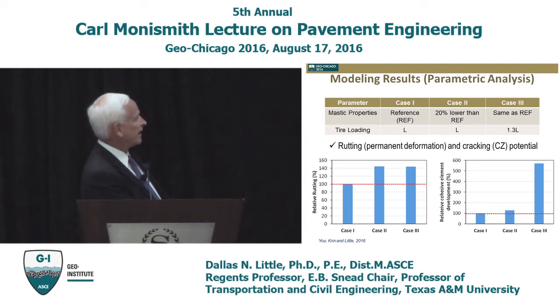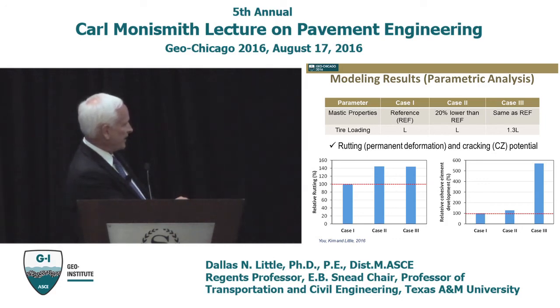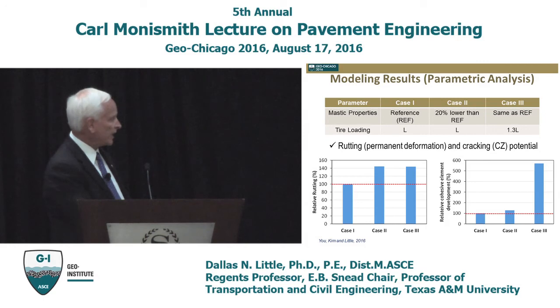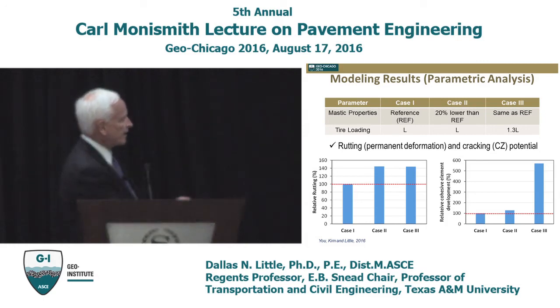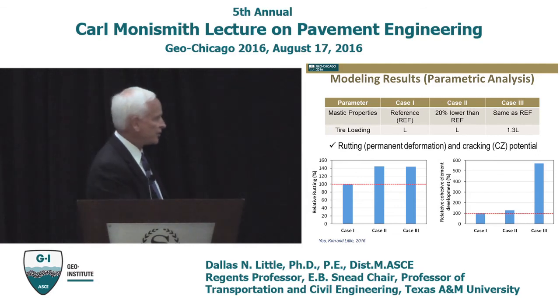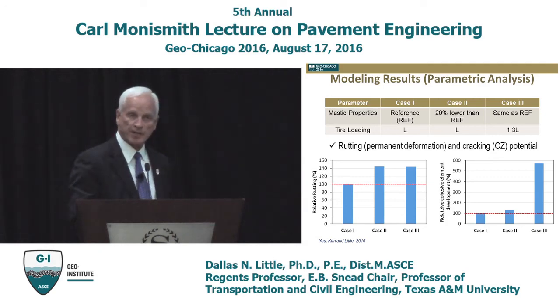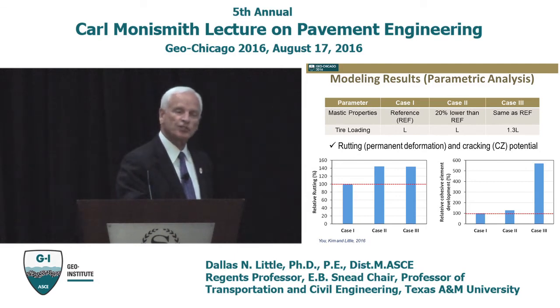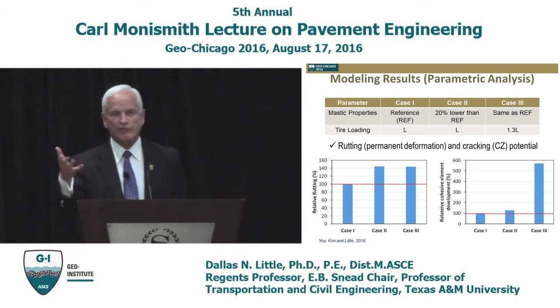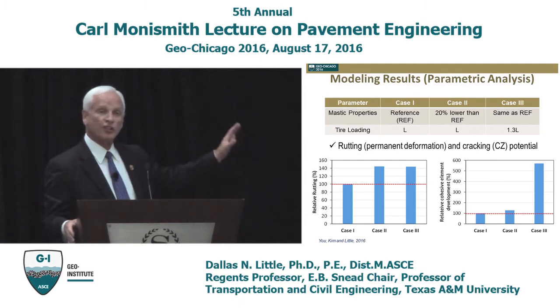And you can see that by looking at relative rutting, case 2 is about equal with case 3, and about 40% more rutting in those two cases than the standard. Over here under damage, which is due to crack development in the cohesive zones, or the cohesive elements, you can see that cases 1 and 2 are about the same, but when you get to case 3, it's 5 times the amount of damage. What strikes me with this, if you compare that with equivalent axle load factors in the AASHTO 1993 design guide, this is a lot different.